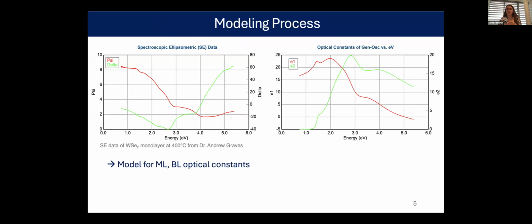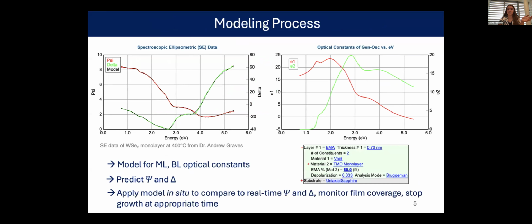I then make a model for the optical constants epsilon1 and epsilon2. Those can then reconstruct a psi and delta model that predicts what it should be for these certain scenarios. So what we can fit for is something like the coverage percentage. So that EMA percent is what percent of the material on the substrate is what we are modeling as the monolayer. So we can get an idea for, at this moment in time, how much of the substrate is covered by the monolayer tungsten diselenide. So if we can apply that in situ, we can get a real-time monitor.